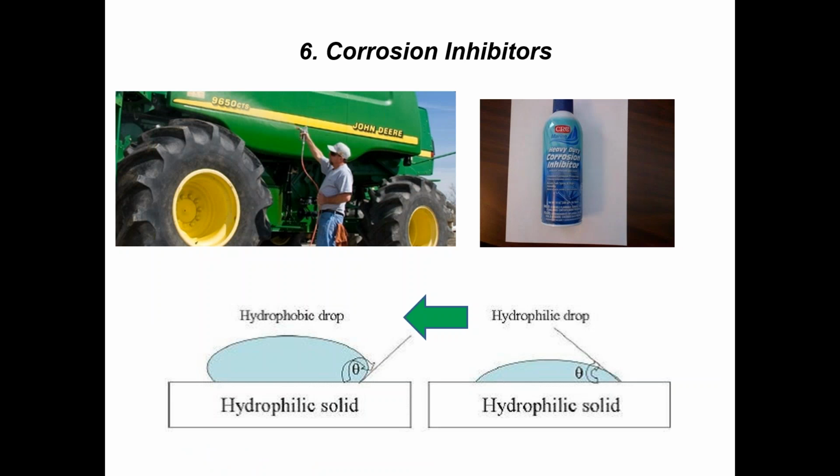Now, after washing, what we recommend is, you've got a dry surface, now it's free of any sort of contaminants or residual salt. What you should do is spray a corrosion inhibitor. Spray-on corrosion inhibitors, basically think about linseed oil. They have a very similar mechanism. They're trying to make that surface, which used to be hydrophilic, likes water, turn into hydrophobic. So that surface will resist water ingress.